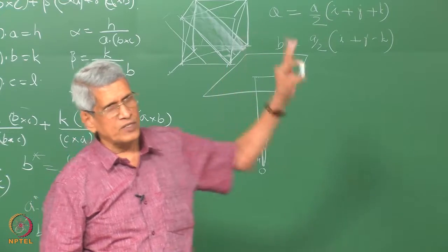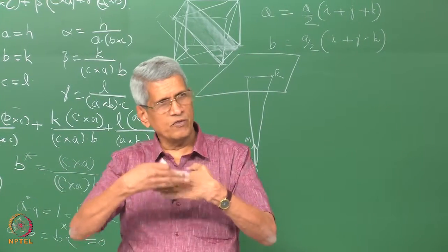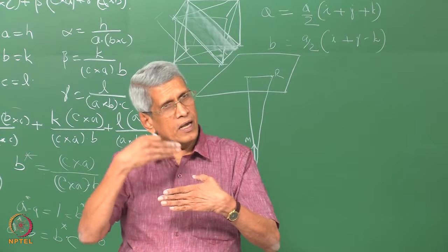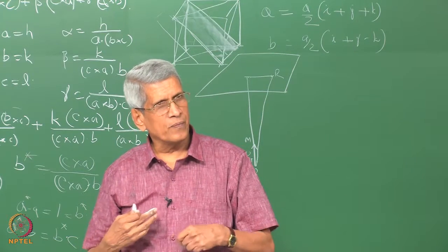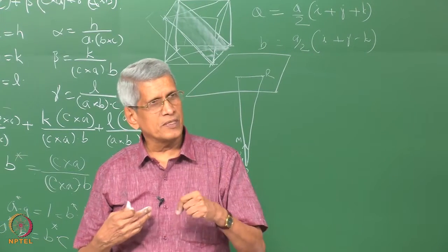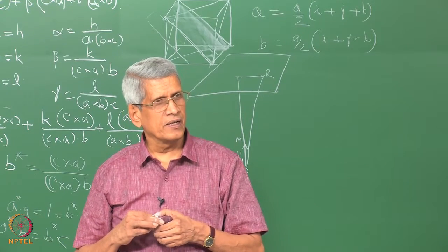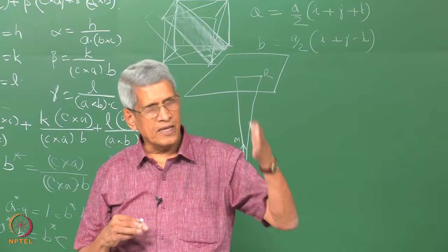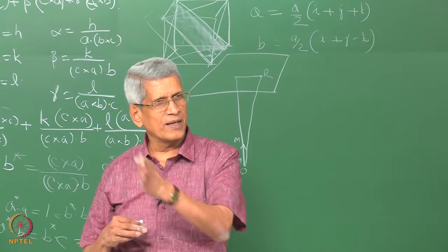This is one way to construct it. Then, since we know the planes, and the vector perpendicular to them, each reciprocal lattice vector represents a particular plane in the lattice, correct. If a plane is indexed as HKL, the reciprocal lattice point can also be indexed as HKL.